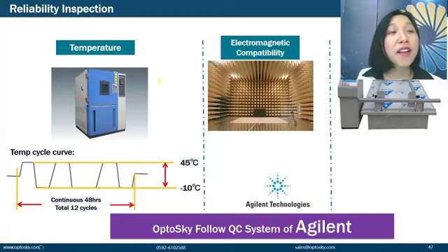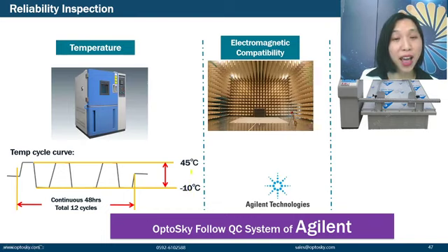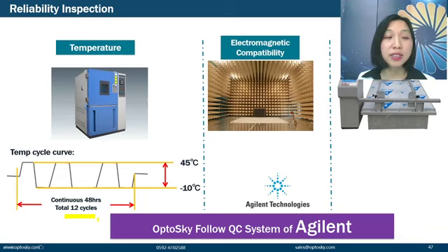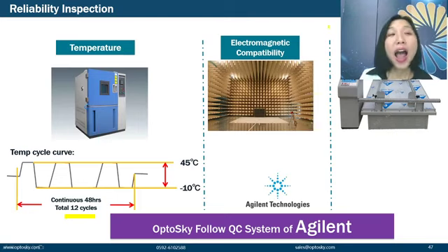Referring to reliability, we also need to mention the inspection tools. We have a temperature test. The temperature cycle curve goes from -10 to 45 degrees, and we perform it continuously for 48 hours, with a total of 12 cycles. And after performing 3 temperature cycles, we can note our temperature reliability is very good. And also we have electromagnetic compatibility testing and a vibration resistance platform. All our reliability inspections are performed by the QC system of Optosky.